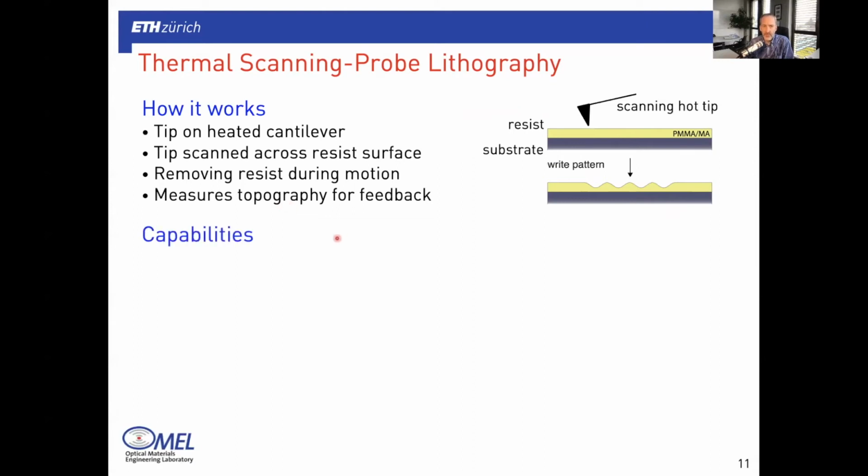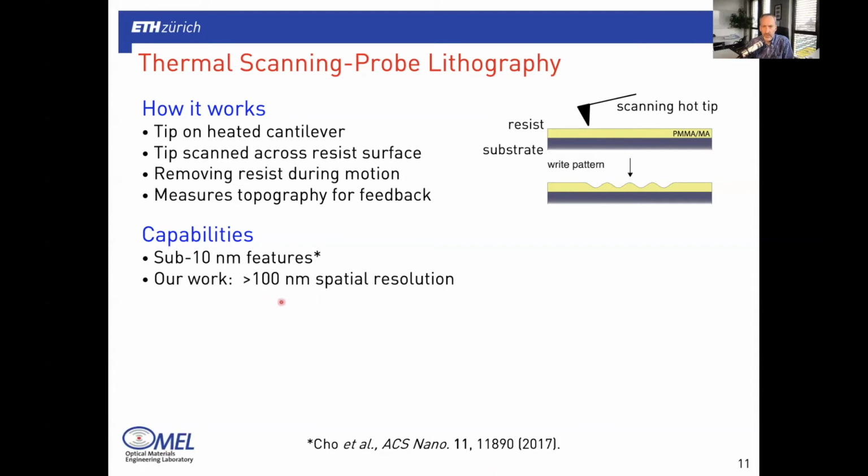And the capabilities of this tool are really amazing in the sense that in the hands of the people that developed it, here's a group at IBM Zurich, you can get sub 10 nanometer features in X and Y, so in the plane. We're going to limit our work to basically above 100 nanometer spatial resolution today in X and Y. More importantly for us is that you can have control on the height, Z direction here, with error of a few nanometers. And also, it's a really simple and flexible approach, as I'll try to demonstrate.